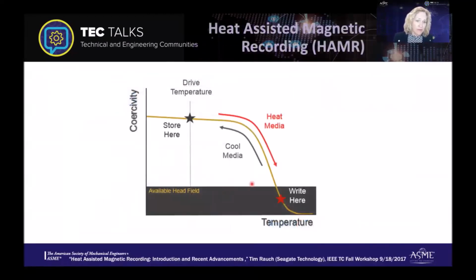And so that's the concept of HAMR, heat-assisted magnetic recording, where you take a disc or medium that can be very high coercivity. And coercivity is that resistance to changing the magnetization at your normal room temperature. And this is our amount of head field. So we can't write while we've got this resistance that's very high. But if you heat the media to a temperature called the Curie temperature, the coercivity actually drops quite dramatically down to a level where you would be able to write. Then you can cool it back off, back to room temperature, and the bits and grains are very stable at that temperature. So in a sense, you can only write where the disk is hot.